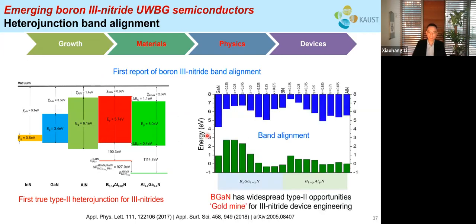In addition to the experimental study, my student has also conducted a DFT calculation of the band alignment for boron gallium nitride and boron aluminum nitride. Just like the boron aluminum nitride on the left here, boron gallium nitride also has widespread type 2 opportunities. This is very interesting. When I saw this result, I told my student that this is really a gold mine. The student can really explore and discover numerous opportunities based on type 2 or the combination of type 2 and type 1 heterojunctions.